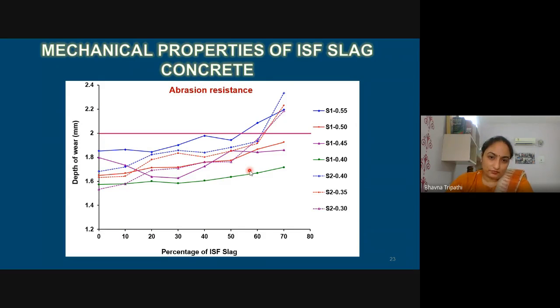Fine particles were missing. And that was the reason that the surface was not very smooth. And when we apply abrasion to a surface which is already not very plain and smooth, then the abrasion depth would obviously be more. So this property can also be adjusted or compensated by adding some fines. However, we did not do it because we wanted to test the actual effect of ISF slag.